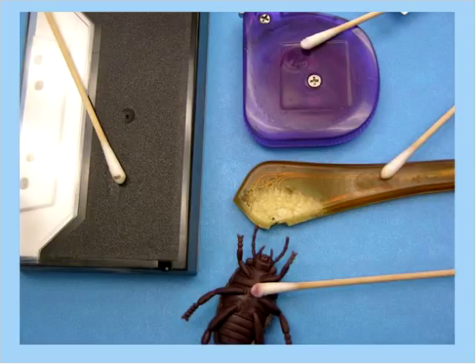Plastics — here are some random plastic items from my lab. I went at each one with a Q-tip with acetone on it. With this one you can see a smeared-up area after it dried — it messed up the surface. Same with the cellulose nitrate handle — you can see the messed-up area. Even if the surface isn't visibly disfigured, as with the cassette tape and the rubber cockroach, pigment came up on the swabs anyway, which means there's some damage happening. Plastics are really difficult to identify without knowing exactly which plastic you have, so it's hard to know which solvent or adhesive won't harm them. I err on the side of not putting adhesive labels on plastics at all, but labeling them with tags or redundant housings.